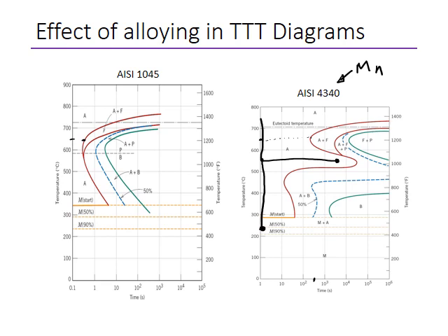So if you are trying to get a 100% martensitic structure in this material, you have to quench the same way as here. But because your material is very thick, it happens that the center isn't following this graph. The center is more like doing something like this.